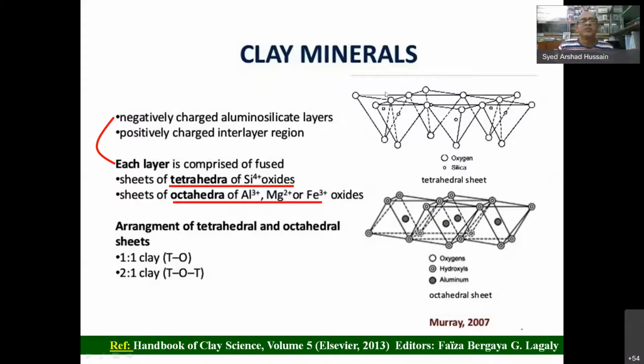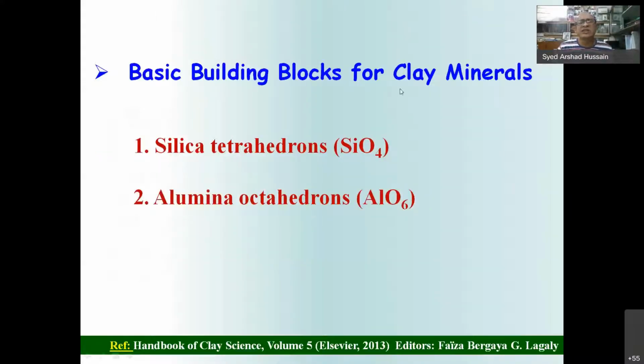Basically, I told you that clay is a layered material, and each layer is composed of basically two sheets. One is a series of tetrahedra, schematically shown here. Then another sheet is octahedra of aluminium, magnesium, iron, etc. They organize in such a way that it is tetrahedra, then octahedra, then tetrahedra, or something like that. In this way, they form a layer, and they stack layer by layer to form a crystal. So the basic blocks of the clay are these sheets, either tetrahedron sheets, maybe silica, or octahedron sheets, maybe alumina or iron, magnesium, etc.